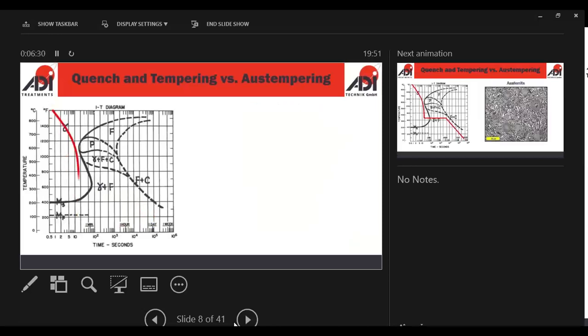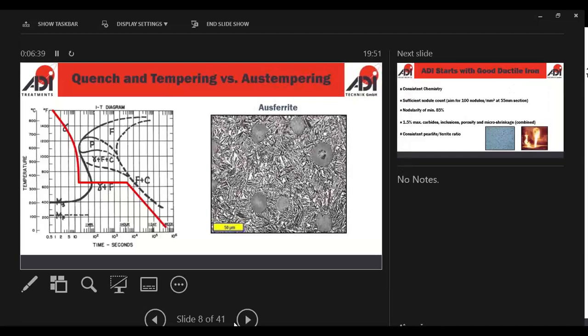With austempering, which you can apply to steel, but is mainly for ductile irons or gray irons, you gain a similar process. You heat the parts up to say 850, 900 degrees centigrade, but instead of quenching into a water or an oil, we quench into molten salt. This allows us to quench between sort of 200 degrees centigrade up to 400 degrees centigrade. And actually the austempering occurs between 250 and around about 380, 390. Yes, you can austemper at 400 or even higher, but in our experience, when you quench at such a high temperature, you do see a reduction in certain mechanical properties, particularly elongation values and impact.